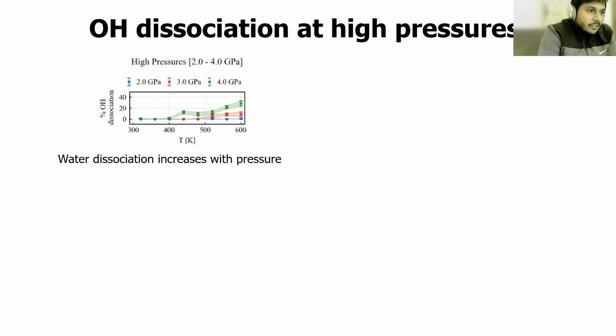And finally, the last bit I would like to show, again related to this phase diagram, is that these potentials are very well capable of breaking bonds, and that's really an improvement over empirical force fields. And it's also an improvement over DFT, where you generally need long simulations to be able to see spontaneous bond breaking. What we found is that when you have water in 2D and you apply some pressure, for example at 2, 3 or 4 GPa, water molecules spontaneously start dissociating.